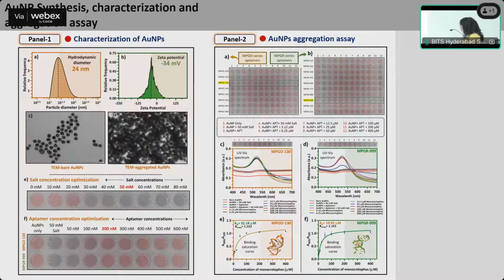Okay. So the next is the aggregation assay. How to know which aptamer is specific and which we have to use for the sensing platforms? So we have synthesized gold nanoparticles to perform the aggregation assay, which tells us which aptamer is binding with the target and leaching out from the nanoparticle surface. So this is the hydrodynamic diameter of the gold nanoparticles, and the zeta potential and TEM analysis, which tells us that the particles are monodispersed.